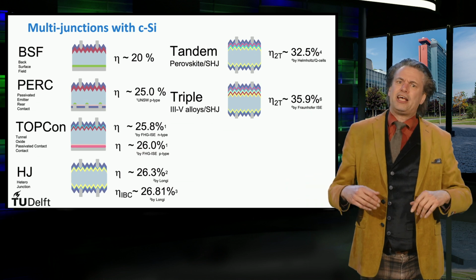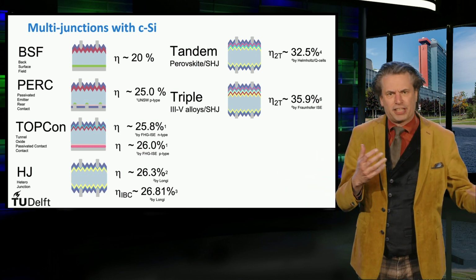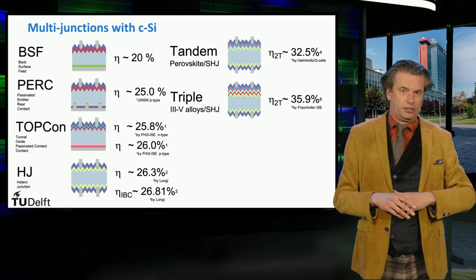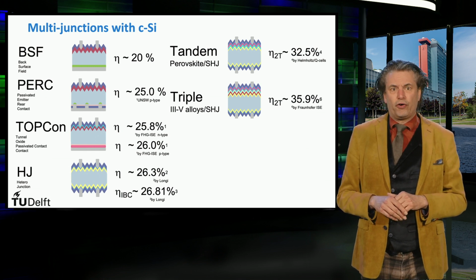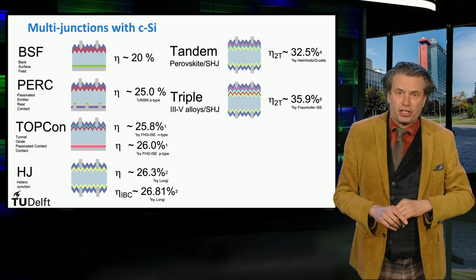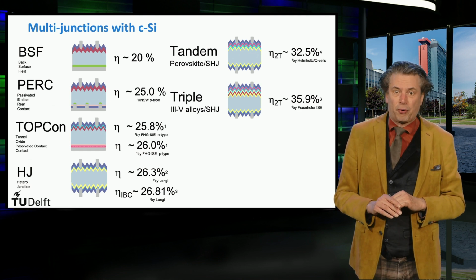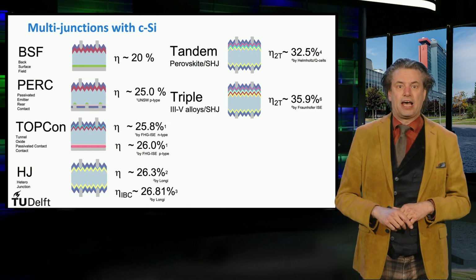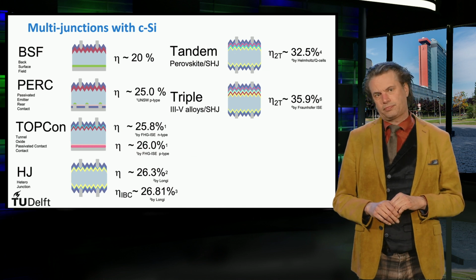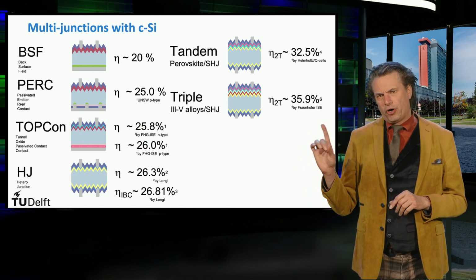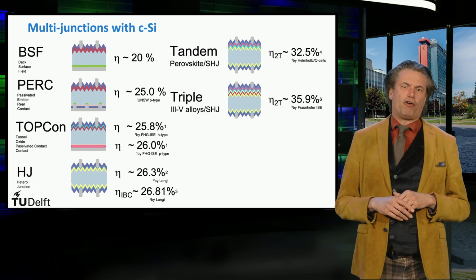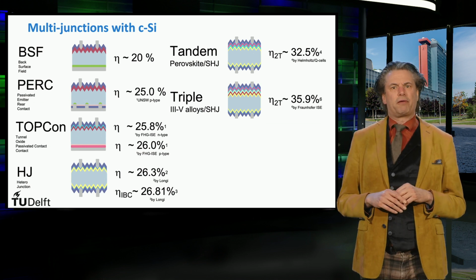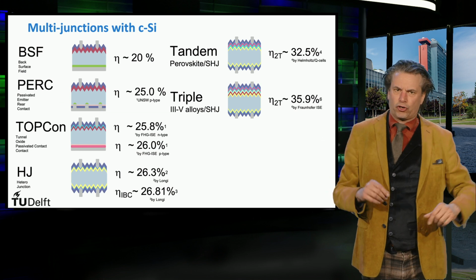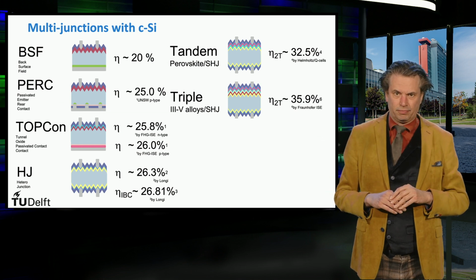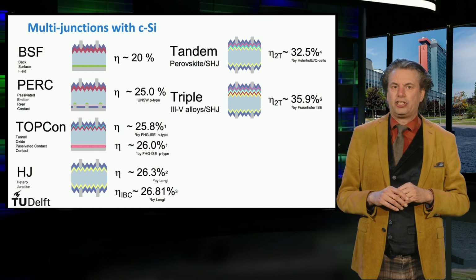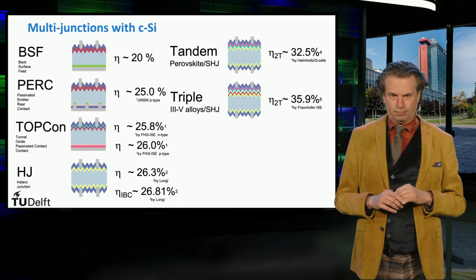Another approach is the combination of the III-V semiconductors with a crystalline silicon solar cell. The record conversion efficiency is based on a triple junction cell with 35.9%, as processed at Fraunhofer ISE. An important note is that the efficiencies of the emerging PV technologies like organic PV and perovskite PV do not correspond to stabilized efficiency. The performance of these cells still suffers from degradation.